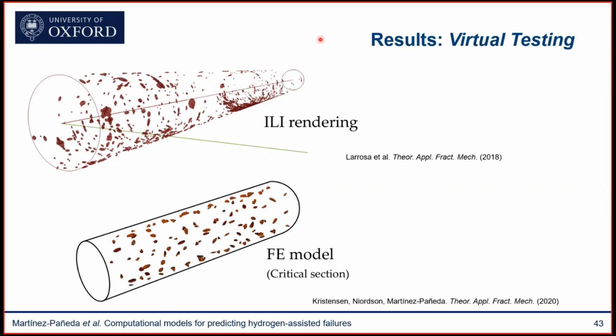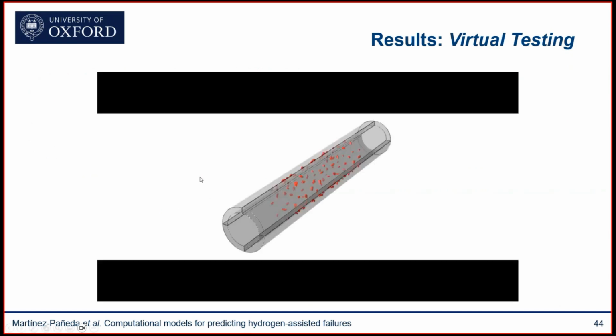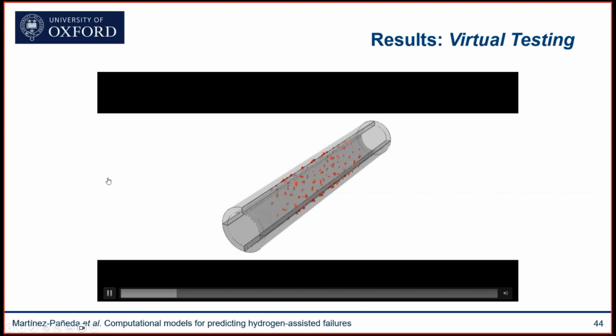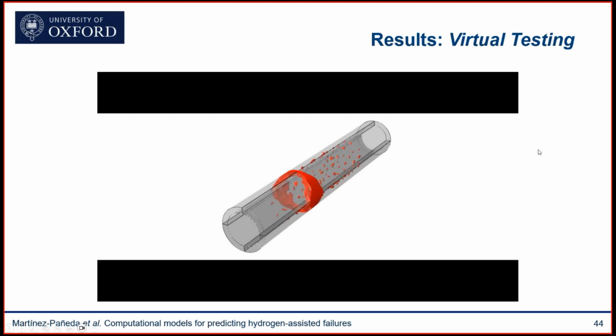So we can model that pipeline. We chose to model a critical section of 3 meters that contains more than 100 of those defects. We can very easily incorporate those defects into our model because we are solving for the phase field as a degree of freedom, so this is basically an initial condition. And then we can subject the pipeline to in-service conditions, and we can see how those defects start growing. You can see how they start growing, how they merge with each other, and then eventually how they extend, and you get a complete collapse and failure of the pipeline.